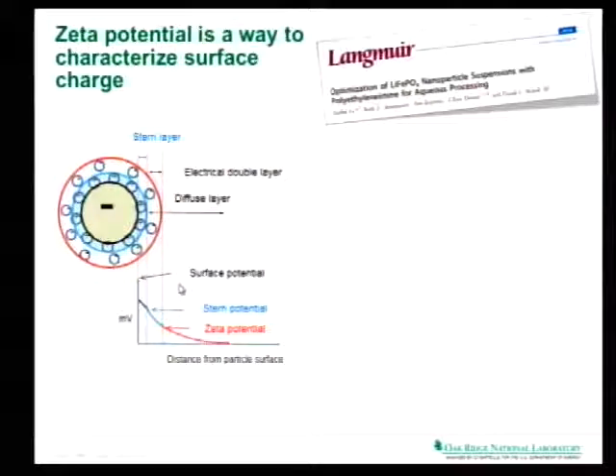So what we were doing is we were essentially looking, how can we make those particles stay in a suspension there, stay afloat in my slurry. And one key thing to look at is essentially surface charges of those particles. When those particles have a surface charge which is too small, too close to zero, they tend to agglomerate because the van der Waals forces are overcoming the repulsive Coulomb forces. So if you're able to modify that in a way, you can keep them afloat.